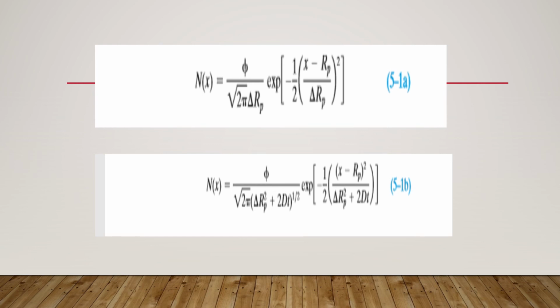But one problem of this doping method is the lattice damage, which results from collisions of the ions with the lattice atoms. However, most of the damage can be removed by simply heating the silicon, which is called annealing. But this heating cannot be done for gallium arsenide because it evaporates.